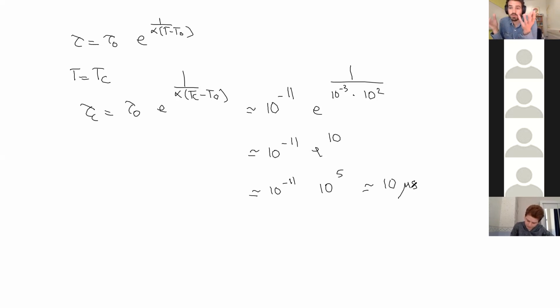Molecular timescales are picoseconds. It's related really to the motion of the molecules when it's alone and not crowded. But then when you are in a liquid environment, well, you have some constraints. The molecules are very densely packed. And so you need some time to jump outside the potential barriers created by the neighbors. And so the liquid timescales are much larger. And so it's more the microsecond. And the glasses, as we will see soon, meaning when T reaches Tg and not Tc, then it can explode and become days, years, and even infinite, because in this description, the timescale is diverging. All right. So you have timescales: atoms, picosecond; liquid, microsecond; and then you start to increase a lot the timescales because you are going to the glass, and the glass can be hours, days, years, and so on.